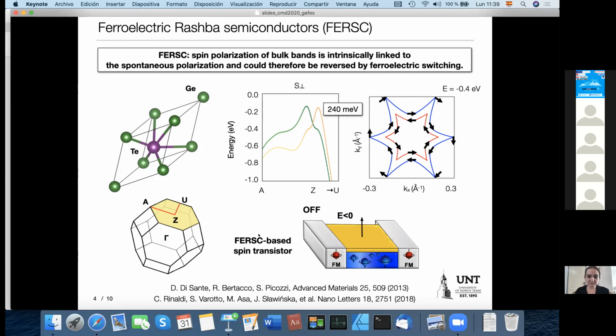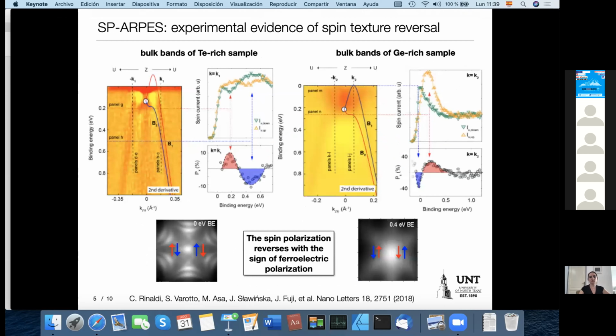But okay, this is theory. This switching of spin texture is not so trivial from the experimental point of view. So we have some achievements also in this field. The colleagues who work on experiment performed ARPES studies. They managed to visualize these bulk bands that I have shown in the previous slide. And they have also performed spin ARPES for these bands and actually demonstrated that for 2 samples with opposite polarization, we indeed have the reversed spin texture. So they demonstrated the link between electric dipole and spin texture.